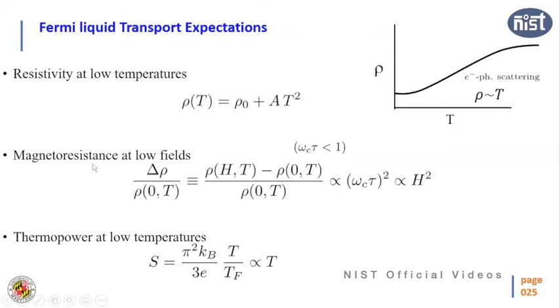And also one can measure the magnetoresistance of this material. Magnetoresistance will also be very similar to this one. You will not see this linear in resistivity or linear in H, but other than that, it will be quite similar to resistivity as a function of temperature. We also measure thermopower. Thermopower for normal metal, if it follows Fermi liquid theory, is also proportional to temperature. So if I divide by temperature, S by T is constant. I'll explain what thermopower is later, I have a few slides.